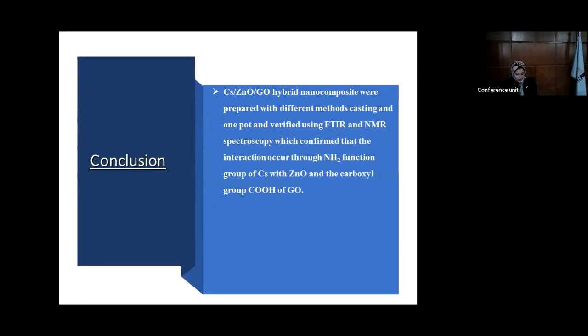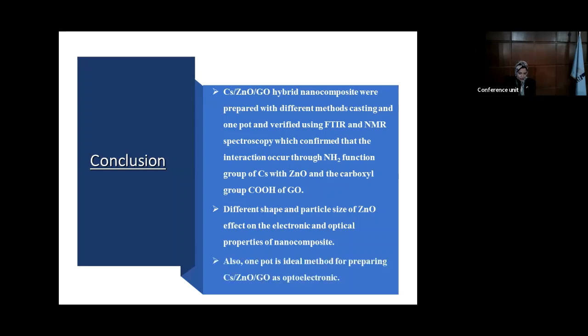Finally, we can conclude that in our work the chitosan zinc oxide graphene oxide hybrid nanocomposite was prepared with different methods, casting and one-pot, verified using FTIR and NMR spectroscopy, which confirmed that the interaction occurs through the NH2 functional group of chitosan and the zinc oxide, and the carboxyl group of graphene oxide. The electronic and optical properties of the nanocomposite are affected differently by the shape and the particle size of zinc oxide. The one-pot hybrid method has the most enhanced properties, which confirms the theoretical model. In addition, the prepared chitosan zinc oxide graphene oxide can be used as optoelectronic material.